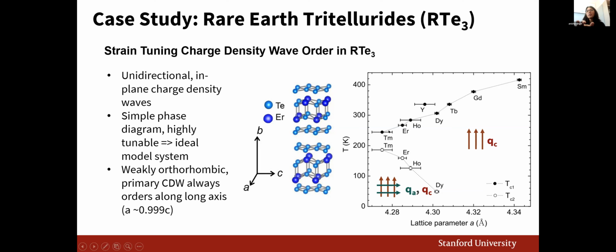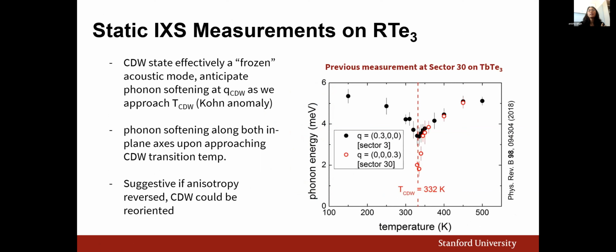And as you can see, for the heaviest members of the rare earth series, these materials actually have a series of CDW transitions. So actually there's a secondary order, which corresponds to CDW order running orthogonal to the primary order, so CDW along the A direction. But for the purposes of everything I'm going to be talking about here, we're really just going to be focusing on this higher temperature transition, which in erbium telluride happens at about 268 Kelvin. Now, the system also has a glide plane, which results in the material being very weakly orthorhombic. But as a consequence of the orthorhombicity, we see that the primary CDW wave vector is always going to run along the longer of the two in-plane axes, which in this case is that C axis. All right. So there have been some previous IXS measurements that have been done on this material family, but statically, not with the application of strain.